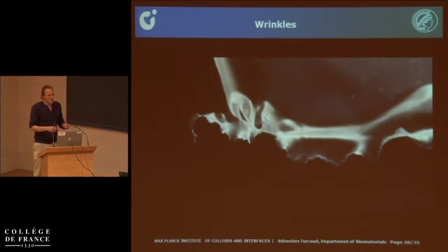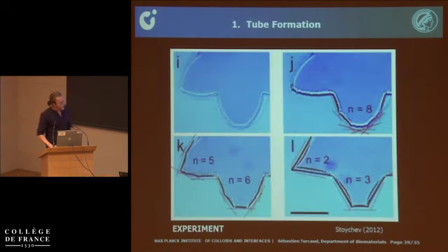This wrinkling here is like a torn plastic bag, where you see this fractal wave. If you take a plastic bag and tear it, then along the sides of the fracture you will have plastification strains that lead to excessive edge length. Here you see this fractal wave that you can also see in lettuce, vegetables, or clothes. And it's confirmed by the experiments. We see here at different time points that the number of wrinkles is very small. Here we start to see them, here we can start to count them, and at some point they stop.